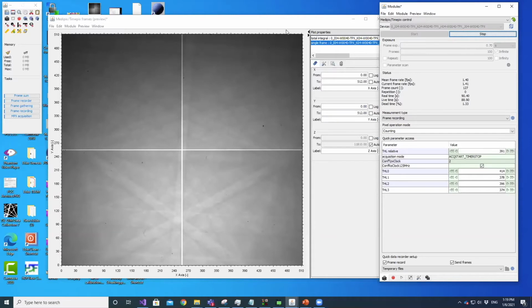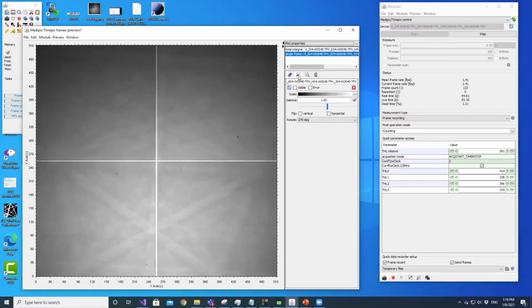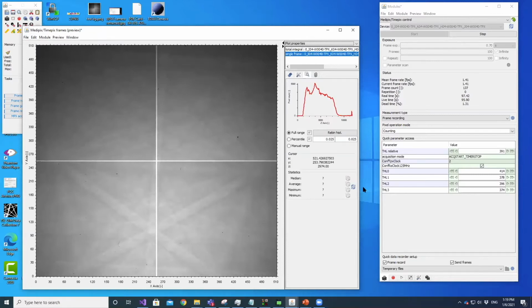What we're able to do when we're running, I'm going to go over here to this little thing here, and I'm just going to say, show me statistics. And as I move my cursor around, you'll see this X, Y, Z value changes. X and Y is just the coordinate within the pixel array space. Z here, though, is the number of events or the number of electrons per pixel. So we're directly counting the number of electrons per channel. If we look at the average right now, we're looking at just under 5,000 electrons on average. The maximum counter here is just under 12,000. So it's essentially about 13.5 bits counter depth we have to count things.